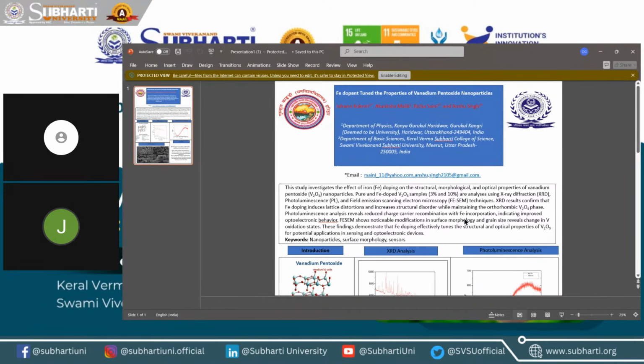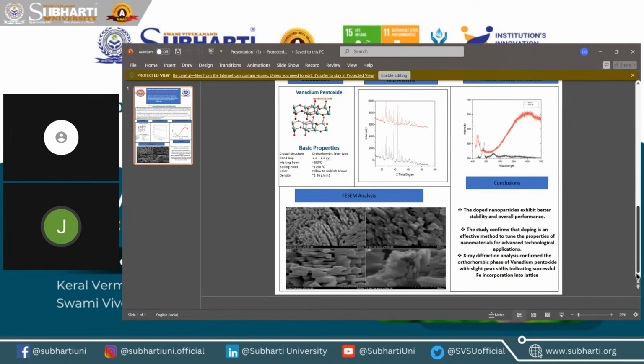In my introduction, I have taken vanadium pentoxide at 3% and 10% doping. The structure of vanadium pentoxide is orthorhombic layer type. Its band gap ranges from 2.2 to 2.3 electron volts. Its melting point is nearly 690 degrees Celsius, boiling point is nearly 1750 degrees Celsius, and color is yellow to reddish brown, with density nearly 3.36 gram per centimeter cube. V2O5 is an important material used in sensors, electronic devices, and batteries. To improve on this work, Fe doping affects the structural, morphological, and optical properties.